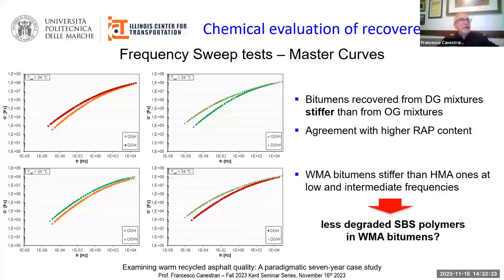Surprisingly, when comparing hot and warm binders recovered from the same type of mixtures, we can see that binders recovered from warm mixtures are stiffer than ones recovered from hot mixtures, especially at the lower and intermediate frequencies. This outcome could be interpreted as a consequence of less degraded SBS polymers in binders recovered from warm mixtures. And this is in perfect agreement with the results of the confocal laser scanning microscopy and atomic force microscopy.